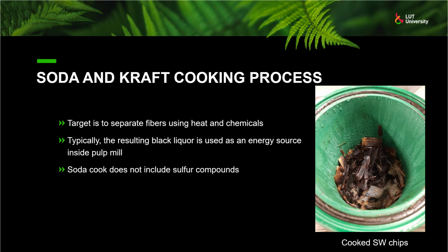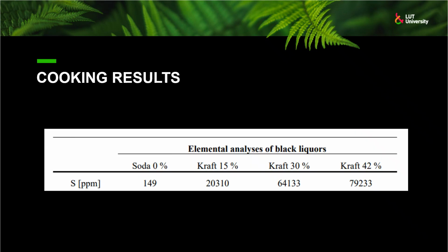In this thesis, 4 different laboratory cooks were done to produce 4 different black liquor samples for lignin precipitations. Cooking results. The laboratory cooks were done at a sulfidity level of 0% as soda cooking, and kraft cooks with sulfidity of 15, 30, and 42%. The produced black liquors were analyzed, and elemental analysis showed that the sulfur contents of the black liquor samples were, as expected, increasing with higher sulfidity levels.